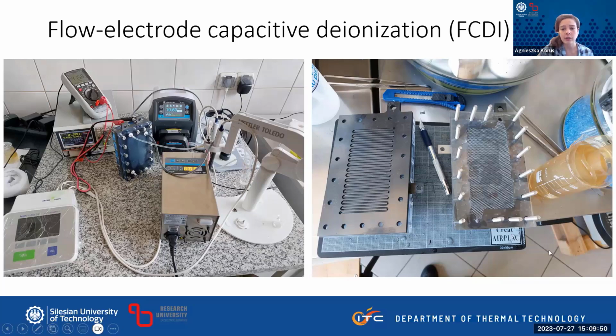On top of it goes the membrane, one of which you can actually see here bathing in the electrolyte solution, waiting to be inserted into the reactor. And then, interestingly, this really thin plastic separator that you can see here, and this net that is fitted inside, this is the water chamber. So where the water is flowing between the flow electrodes. So if our pathway is around 2 millimeters deep, the pathway for the flow electrodes, the chamber for the water flow is 0.5 millimeter wide.